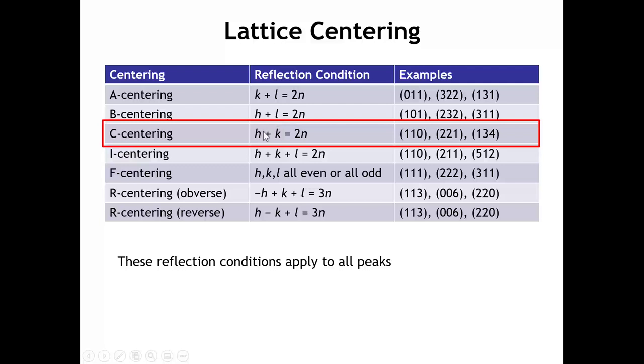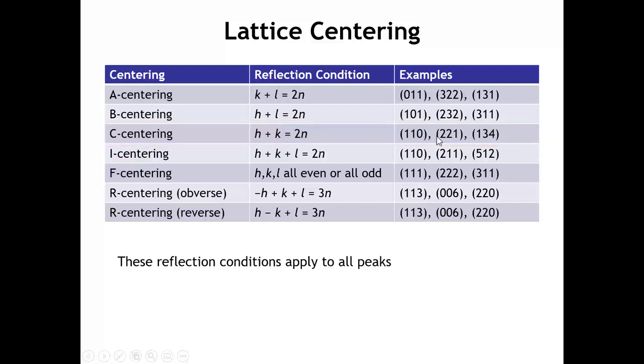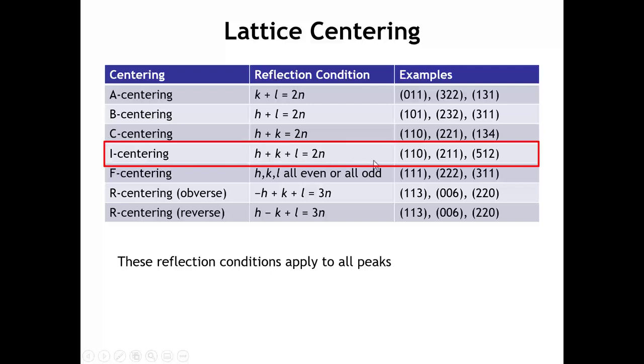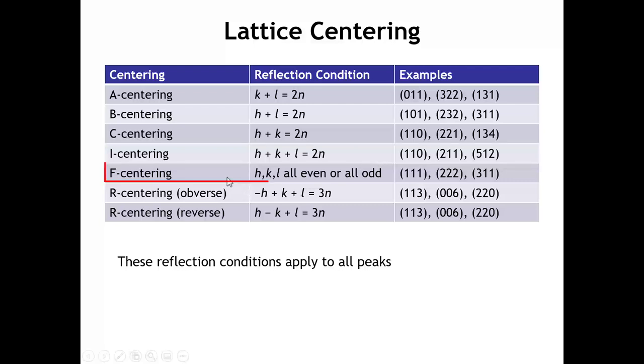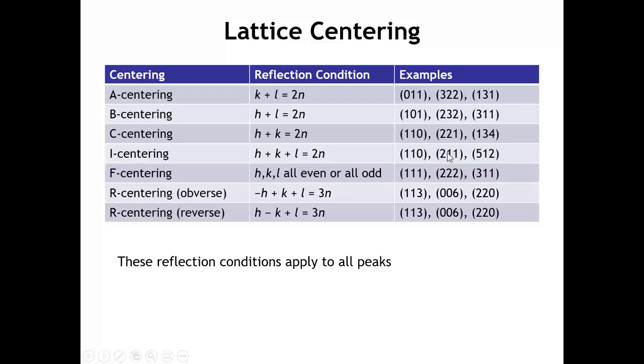Examples where H plus K equals an even number include 1-1-0, 2-2-1, and 1-3-4; the value of L is irrelevant. For a body-centered lattice, when we add all three Miller indices together we have to get an even number. For a face-centered lattice, either H, K, and L all have to be odd numbers — like 1-1-1 or 3-1-1 — or they all have to be even numbers like 2-2-2; we would not see a peak like 2-1-1 because that's a mixture of odd and even. And for the rhombohedral unit cell, the difference between H and K plus L has to be a multiple of 3N. These systematic absences or reflection conditions affect every peak in the pattern.